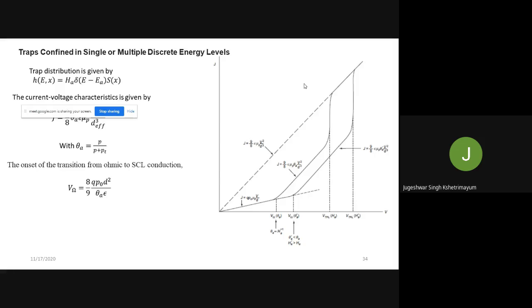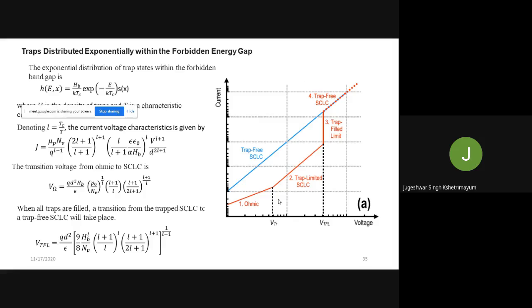However, in the case of exponentially distributed levels, after the ohmic region comes the trap limited region, where the traps start filling slowly, and after completely filling the traps, the conduction continues again. But the slope of this one and the slope of this one should be different. This should be more than 2 and this should be 2. But slightly here, the slope difference is very low and not easily visible.